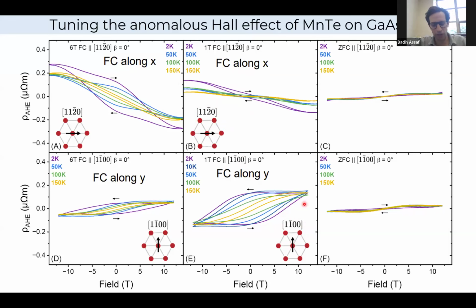With magnetometry, it's difficult to probe whether it lines up with it in this case and doesn't in that case. So we have to do something involving neutron diffraction to answer this question. The hypothesis is that it's only allowed if it locks in. Okay. It locks into 1, -1, 0, 0 upon field cooling. Yeah, essentially that's one hypothesis, that it locks into this direction no matter which direction you field cool it in. And there's a reason why it might do that. Right.